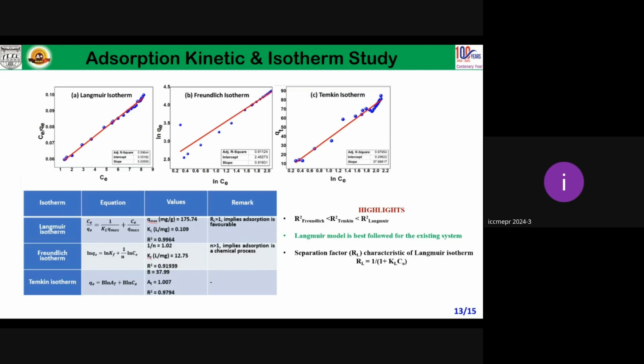Isotherm studies were also conducted, like the Langmuir, Freundlich, and Temkin isotherms. From the results we got, the R square value was higher for the Langmuir isotherm, which suggests that this model gives the best fit to our system. Also, the separation factor RL value, characteristic of the Langmuir isotherm, was calculated, which lies between 0 and 1, which simply implies that adsorption is favorable in our case.